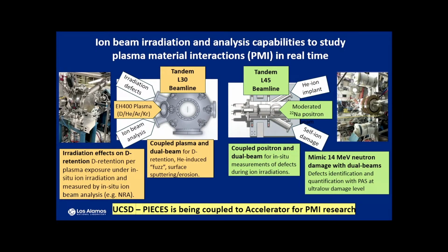At the same time, we're also setting up the positron setup in our laboratory, to look into very tiny defects like 0.1, 0.2 dpa type defects, which are very difficult to see with TEM. TEM is another technique people use to look into the damage production there. But for anything less than 0.5 dpa, defects are so small that TEM is unable to see them. So positron is a very sensitive technique. You can look down to 10 to the minus 7 dpa. So we're in the process of doing that.